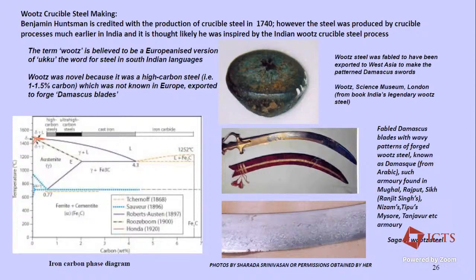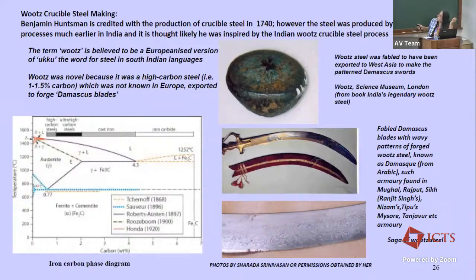And this, as I will explain later, was a process where they're actually carburizing the low carbon wrought iron in crucibles, which were packed with carbonaceous material so that the carbon got into the wrought iron and you got a high carbon steel of about 1.5% carbon. And the speciality of this particular Wootz ingot was that when it was forged, and anyway, I'll go into that later, it also had some other properties such as superplasticity, which is high formability at high temperatures. So it could be forged quite extensively. And also when it was etched, you got these alternating patterns of the low carbon pearlite and high carbon cementite, which is part of the intrinsic structure of 1.5% carbon steel. And these patterns were also quite attractive.